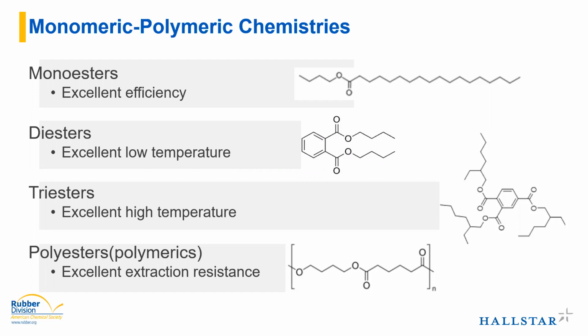Diesters are probably the most common, the most widely used monomeric esters out there. They have 2 ester groups, as you can see here. These are things like your DOA, your DOZ, your DOS. Essentially, any plasticizer where you see a D in front of it is almost always a diester because that D usually means di. Diesters give excellent, excellent low temperature properties most of the time.